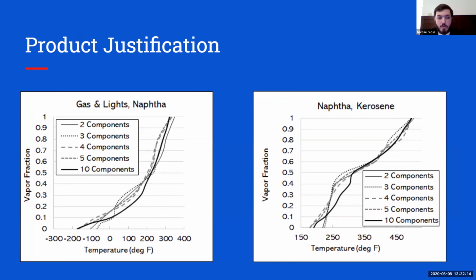And essentially the way our product justification was performed was by taking a baseline of 10 components and passing those through our simulation to see where the boiling points would lie and what range of temperatures our product would boil at. And then we were able to back down those number of components from 2 and start going back up all the way to 5. And we were able to track the curvature of those lines and compare them to our base case. For most of our cut fractions, we were able to use either 3 or 4 components. And this was just due to the shape of those lines overall and how closely they fitted to our base.